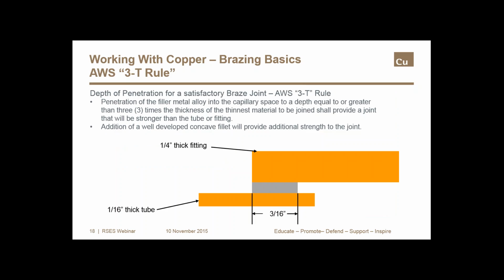The American Welding Society, or AWS, has developed what they call the 3T rule. It says that if the brazed alloy can penetrate the joint a distance of 3 times the thickness of the thinnest material, which is most often the tube, then the finished brazed joint will be stronger than the tube or the fitting. So the message from the American Welding Society is to shoot for deep penetration of the brazed alloy. And the technique used to heat the joint during the brazing process will be an important factor in achieving that penetration of brazed alloy.